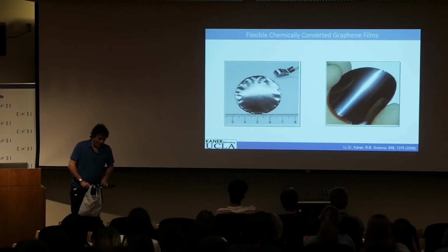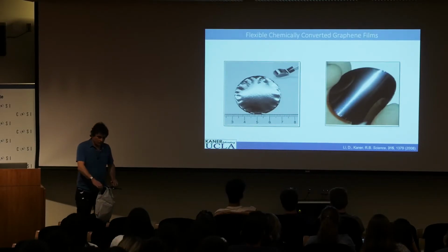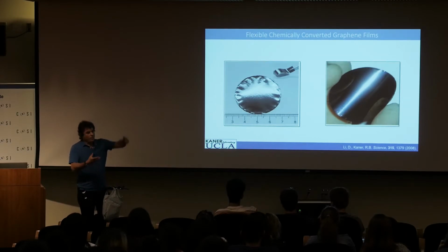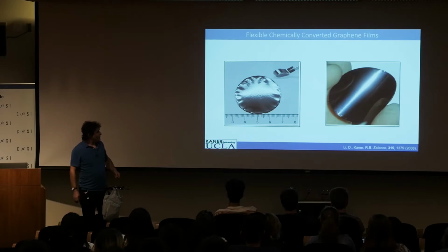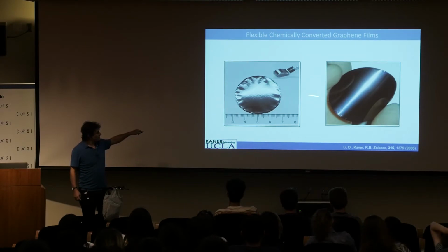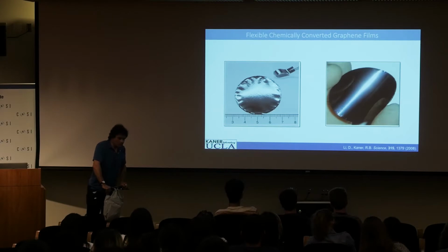Okay, now, because that's scalable, we can make as much as we want. So we make a beaker full of it, we run it through filter paper, and we trap all the layers of graphene. And we do that, we can peel it off the filter paper. So this is pure graphene paper. And you can see how flexible it is, and you can see your reflection here. This is a paper we published in Science about 10 years ago.